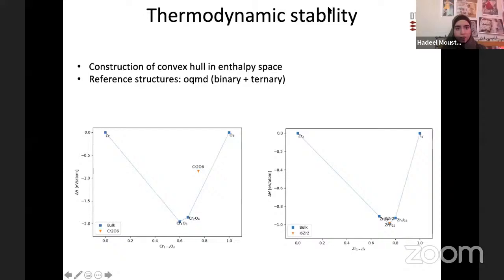For the thermodynamical stability, the convex hull is constructed in the enthalpy space. And as we can see, the blue line is the convex hull, and the blue points here are the bulk reference structures, which are all from the OQMD. And the orange points here are our compounds. So all the materials that are lying at the convex hull are stable, which means that this one is unstable.